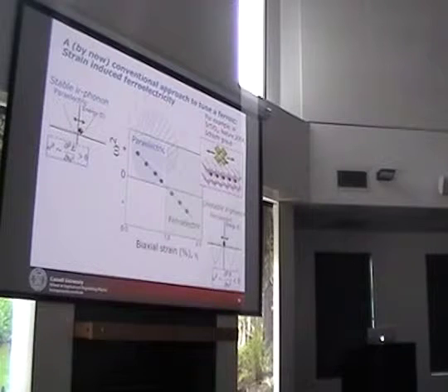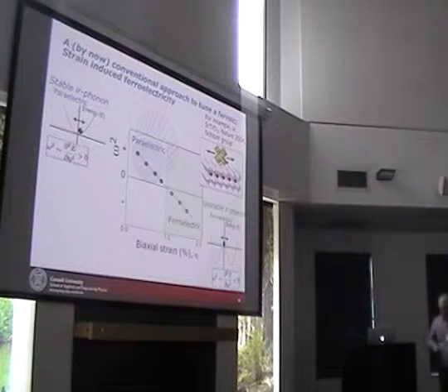The system loses rigidity to that motion and freezes in the structural distortion associated with that force constant. This is how we describe the onset of ferroelectricity in materials like barium titanate, this idea that a polar soft mode freezes in and stabilizes the ferroelectric phase. So you can imagine, if this is your cartoon of that force constant, this phonon happily vibrating in this nice paraelectric well.